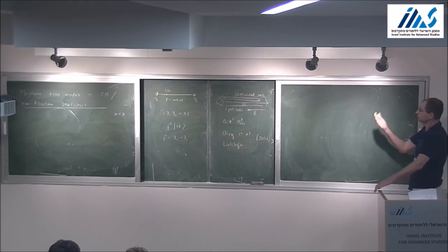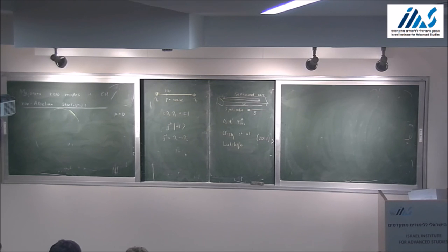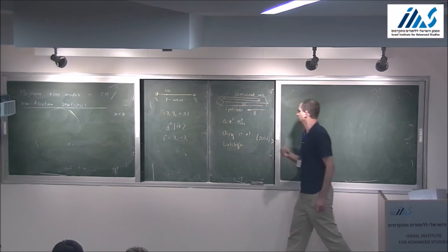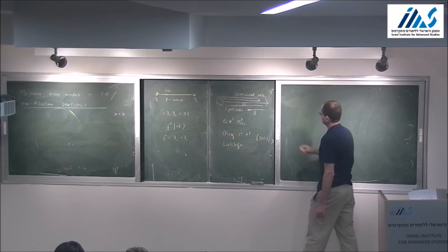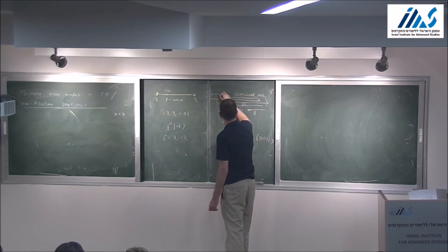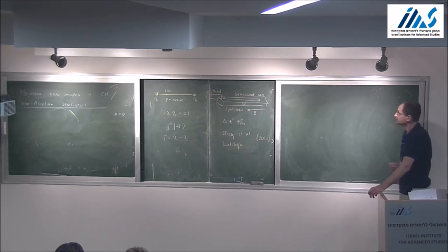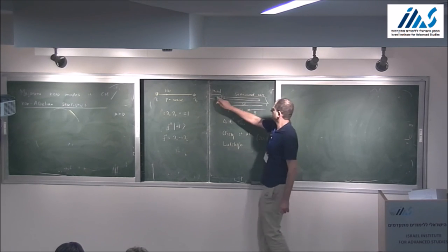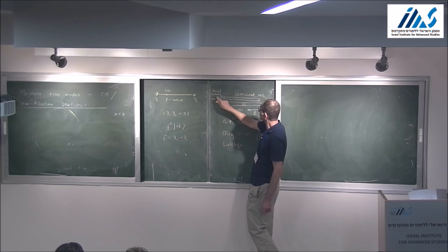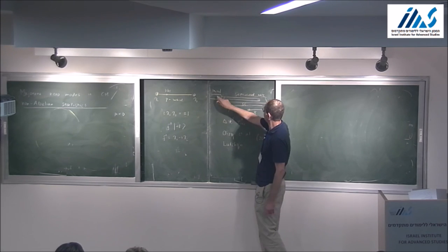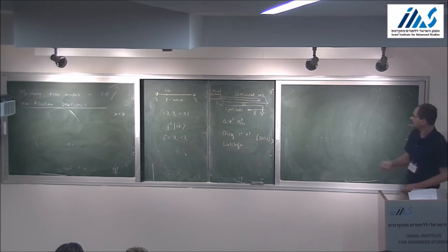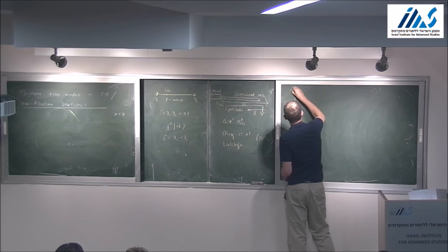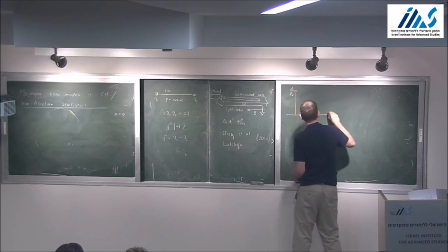Very soon this kind of setup was realized in experiment in quantum wires. What people actually measured is, you basically contact this quantum wire to a metallic lead, apply a small voltage between these two systems, and measure differential conductance between this metal and the superconductor, which is say grounded. And what you're supposed to see, this is dI/dV, and this is the voltage.